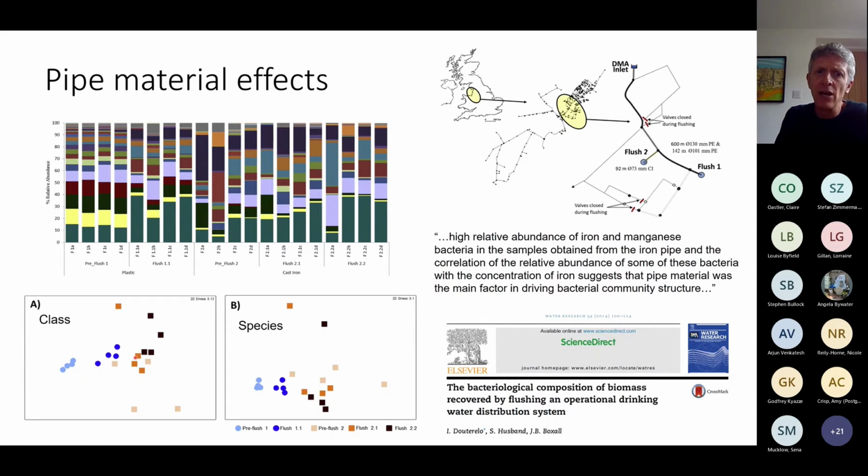So we're definitely more prone to using the substrate material as a source of iron itself, and more of them proliferated and managed to colonize over there in the cast iron pipes over the years of its service. So the substrate material is important. That's my one foray into this talk. Everything else you're going to see is from the plastic pipe loop. But substrate does have an important role.